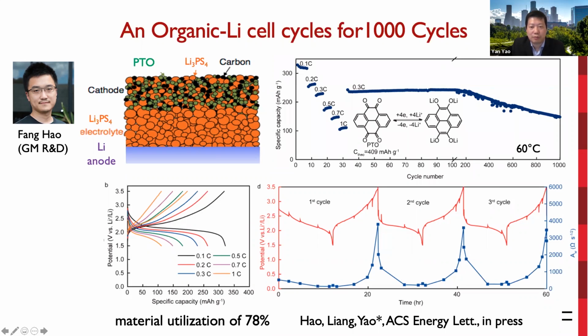We note that when NMC is used in solid-state cells, a thin oxide layer coating is necessary. Otherwise, we will see an irreversible increase of interfacial resistance. The fact that no coating layer is required for PTO is due to its moderate working potential, which enables a longer cycle life for this battery design.